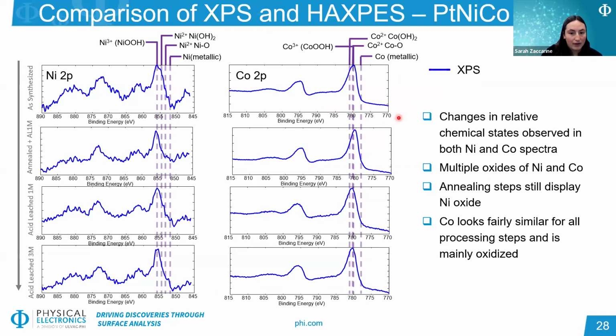We did a similar comparison for the platinum nickel cobalt data set, and here we're looking at the nickel chemistry and cobalt chemistry with the as synthesized catalyst, and then compared to 2 samples that were directly acid leached and a sample that was annealed and then acid leached. So here we have slightly less nickel signal because, again, this is more a thin nickel surface coating. We do detect mainly nickel oxide present with this XPS source. There's not really a strong nickel metal signal with the XPS looking more at the surface. And looking at the cobalt chemistry, which is coming from that bulk cobalt core, these generally look a lot more similar for all of the different processing steps and are predominantly oxidized in the detection limit of the XPS technique.